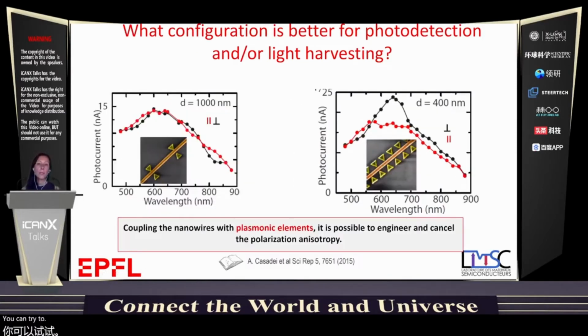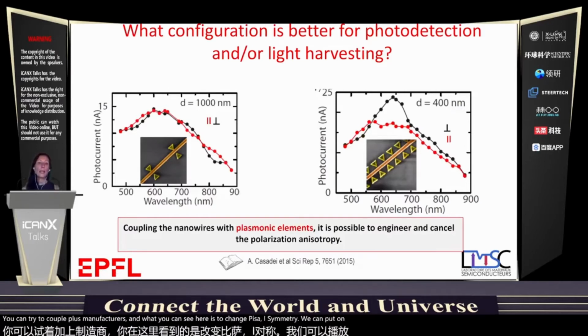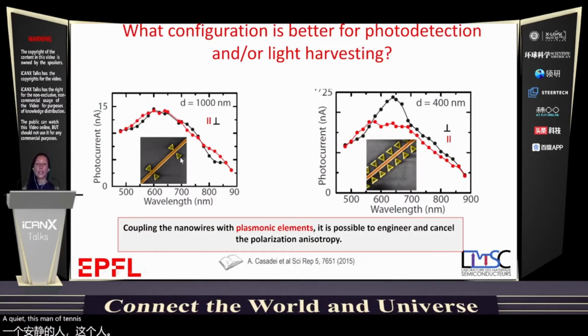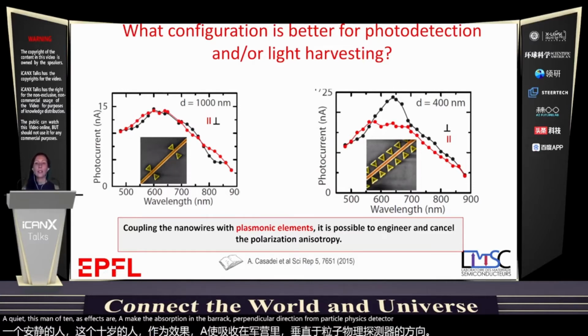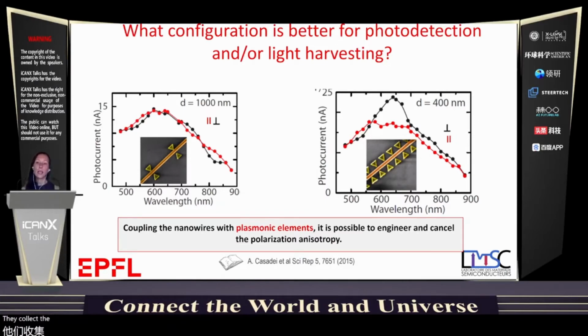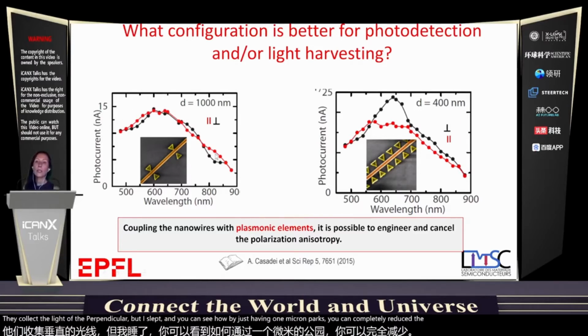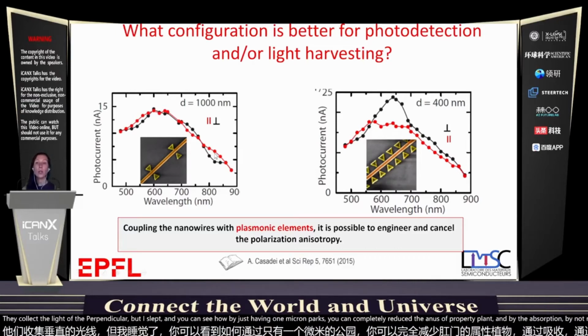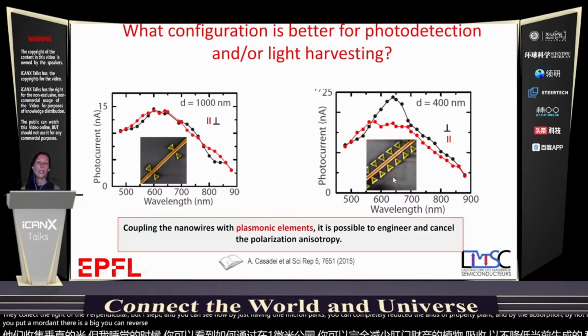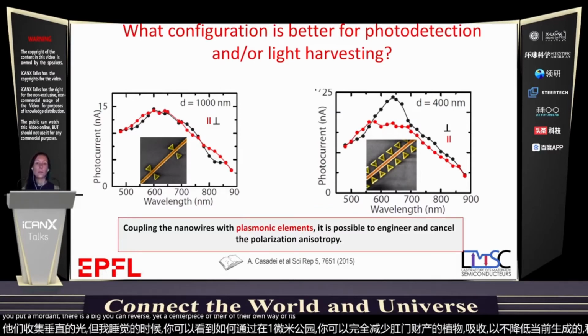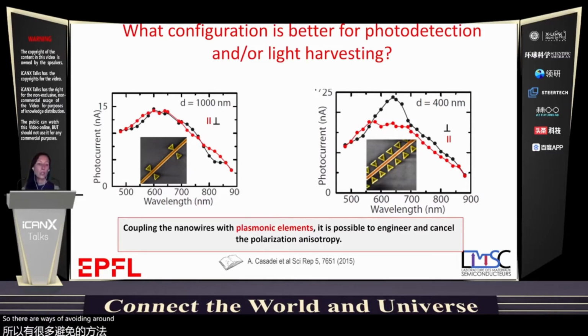You can try to couple plasmonic structures, and what you can see here is to change this symmetry. You can put some bow tie antennas, and by just putting one every micron along the nanowire, these nanoantennas, in fact, make the absorption in the perpendicular direction much more feasible. In fact, they collect the light of the perpendicular polarized light, and you can see how by just having 1 micron apart, you can completely reduce the anisotropy of light absorption without reducing at all the photocurrent generated. And you see here when you put more antennas, in fact, you can reverse the anisotropy of the nanowire absorption. So there are ways of going around the anisotropy of the nanowires.